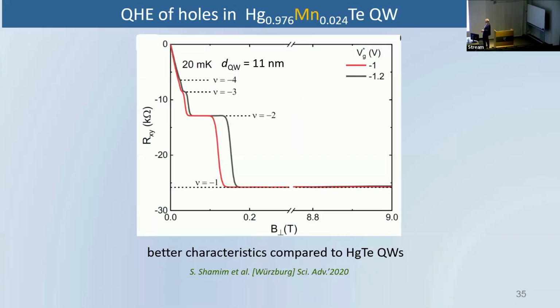If you take the manganese sample, you see that this Hall effect starts at even lower magnetic field, of the order of 100 millitesla, and this plateau continues till 9 Tesla. Why does it continue? Because you have this acceptor state degenerate with your Landau levels, and electrons are taken from this acceptor state to the increasing density of states with the magnetic field, and you have a very wide plateau in this material. So you see the role of impurities very clearly here.